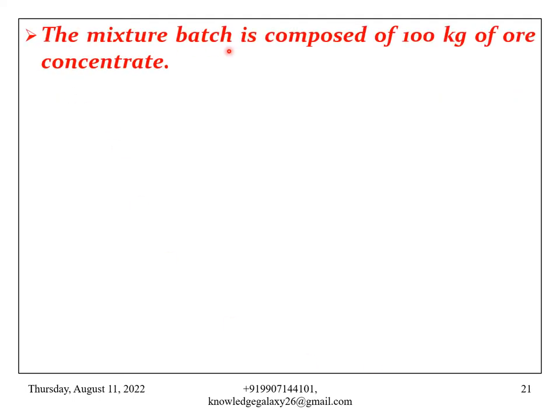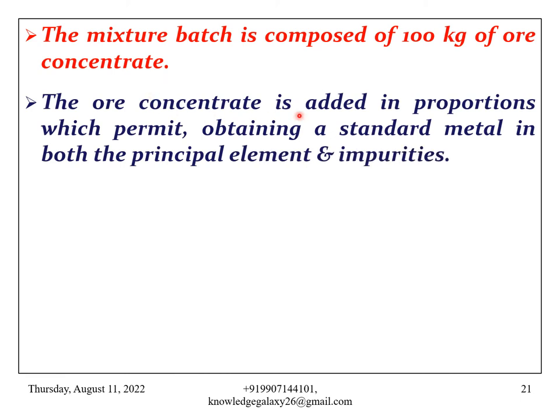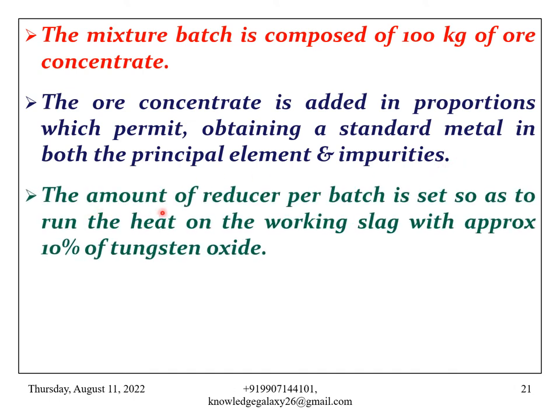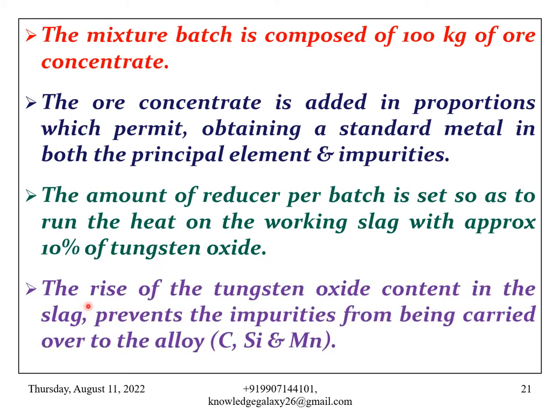The mixture batch is composed of 100 kg of ore concentrate. The ore concentrate is added in proportions which permit obtaining a standard metal in both the principal element and impurities. The amount of reducer per batch is set so as to run the heat on the working slag with approximately 10% of tungsten oxide. The rise of the tungsten oxide content in the slag prevents the impurities from being carried over to the alloy. The main impurities are carbon, silicon, and manganese.